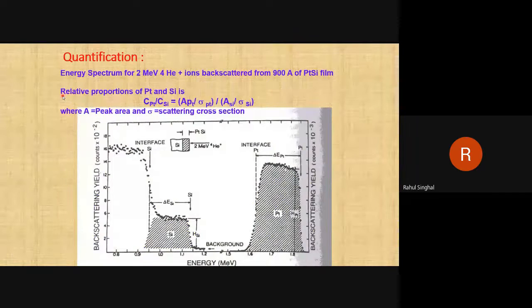Okay, so let's see this graph. This is the experimental data. Here in this figure you can see our material is deposited on silicon. Silicon is the substrate, and in this shaded area it has platinum as well as silicon. So our sample contains Pt and Si, and this is a thin film deposited on silicon. And we are doing measurements with 2 MeV helium ions. So experimentally, you will get this kind of data. These are the dots you will get experimentally.